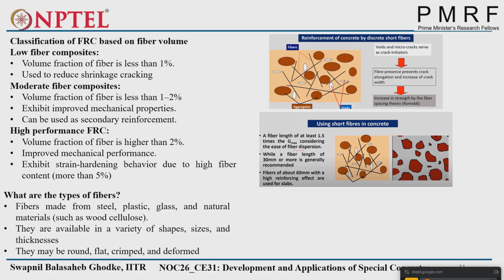The orientation of the fibers or distribution of the fibers also has main importance as a parameter in the design of fiber reinforced concrete. Using short fibers in concrete, most important, the fiber length should be at least 1.5 times the maximum diameter of the aggregate. This is the thumb rule. Whatever the maximum size of aggregate you are using, the length of the fiber should be more than 1.5 times that aggregate diameter.